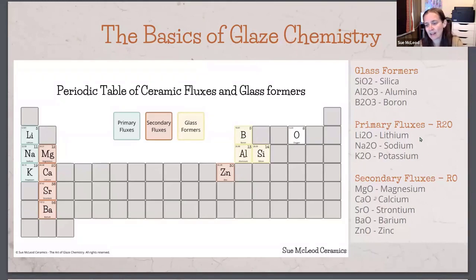So we kind of have to balance out the fluxes, which lower the melting temperature, and the alumina that brings it back up again. And then boron is also a glass former, but it melts at a much lower temperature than silica and alumina. And it is often used in glazes that melt below cone 10. So cone 6, cone 04, earthenware, mid-temperature stonewares, all of those temperatures below cone 10 require a little bit of boron just to get them melting.